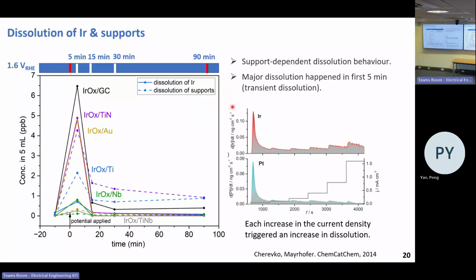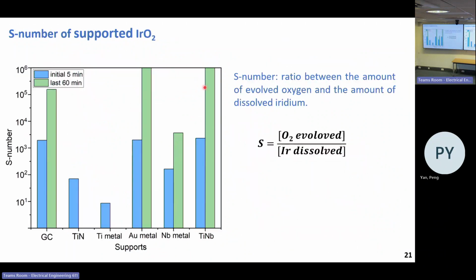So here we showed a support-dependent dissolution behavior. You may have noticed that the highest dissolution always coupled with the highest activity. So how can we combine stability and activity? Here comes the figure of merit called the stability number, defined as the ratio between the amount of oxygen evolved and the amount of iridium dissolved. We calculated the stability number of supported iridium oxide and found titanium niobium alloy showed a similar stability number to gold.